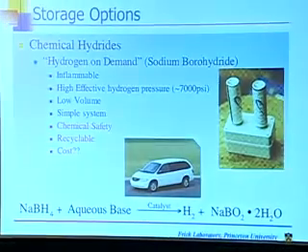One approach that is being considered is an electrochemical approach, where you would take sodium borate and electrochemically convert it to sodium borohydride. We've started actually working on that in our laboratories. You need a good electrocatalyst for that, which is what we're interested in, and appropriate electrolytes. You're obviously not going to do this in water for the obvious reasons. So it's a non-aqueous system.